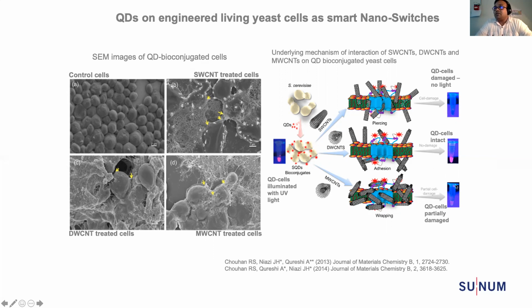How do we see this one? We can actually see these reactions taking place here. As you see, under normal conditions, when there is no external stimuli, the cells start to emit light from their quantum dots on their surface. When the cells get damaged, there is no light because of the quenching taking place between the quantum dots on the surface and the carbon nanotube, which is a well-known phenomenon.